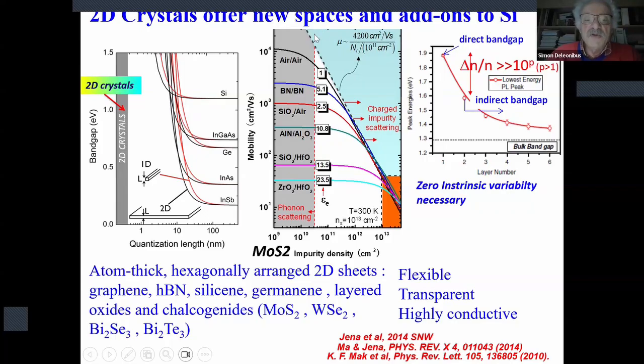It's not very easy to deal with these materials because basically their transport properties, so you can see the mobility as a function of impurity density in these films, their properties will depend on the interfaces, above or bottom interface. So you can see that the low field mobility varies really drastically. So it's extremely difficult to handle these kinds of technologies. Moreover, you can see on this example, this is for MoS2, the same as on the left-hand side.